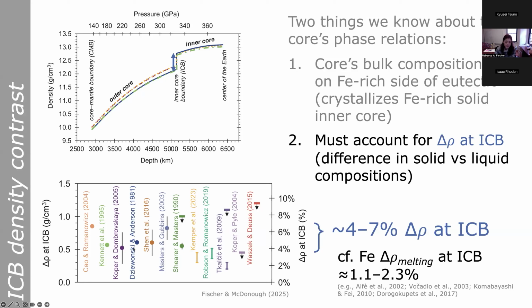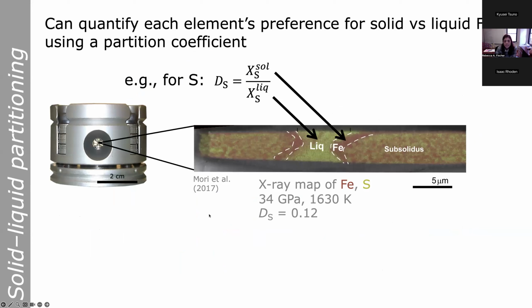You can see that they're all roughly in the ballpark of 4 to 7% increase in density at the inner core boundary. So for comparison, the change in density in iron when it melts at these kinds of pressures is something like 1 or 2%. That's the density difference you get just from changing from a solid to a liquid without any change in composition. So that accounts for part of this density difference, but not most of it. So we want to quantify each of these light elements' preference for solid versus liquid iron. We can do this using a partition coefficient D.